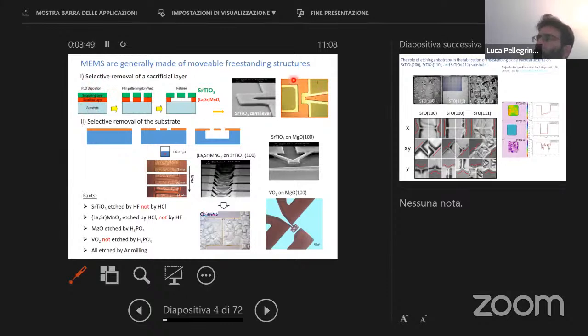And this is an example of a strontium titanate cantilever. Strontium titanate is a well-known oxide that we employ for growing a lot of oxide materials. It is an insulating oxide. So if we make a sacrificial layer with manganese oxide, we can fabricate the pattern, and then we can release it using hydrochloric acid, because hydrochloric acid does not affect strontium titanate. So we remove the material below the film.